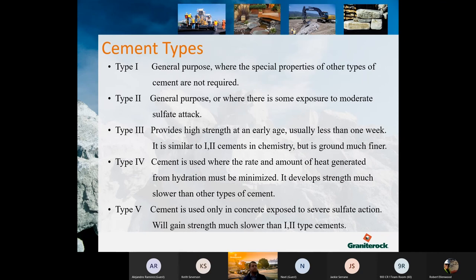Type four is used in applications where the heat of hydration needs to be minimized. When you're working on very large structures such as dams, a lot of concrete together can actually get too hot and negatively affect the concrete, even blow it apart. So this is where that is used. However, it's very rarely used. We haven't seen it in our market.